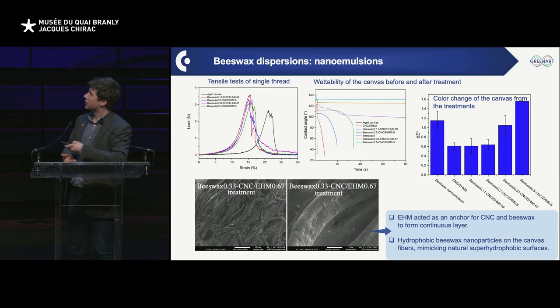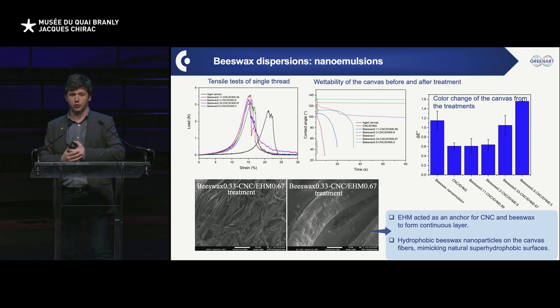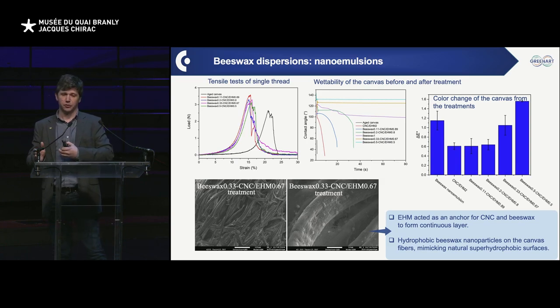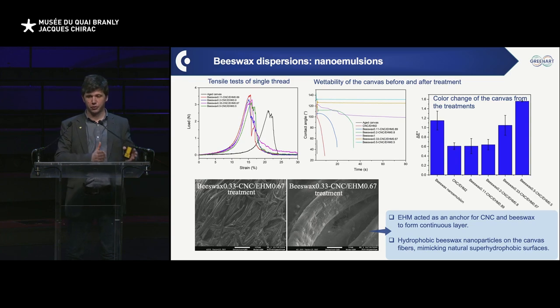And what we can clearly see is that, well, we restore essentially some of the mechanical properties. We reduce the strain that is due to the loss of the mechanical properties due to aging. And at the same time, from this plot, you can see that we are basically decreasing substantially the wettability of the canvases after such a treatment. So that implies that the treatment reinforces it, and at the same time makes it a little bit more hydrophobic, which will make it less prone to sensitivity.